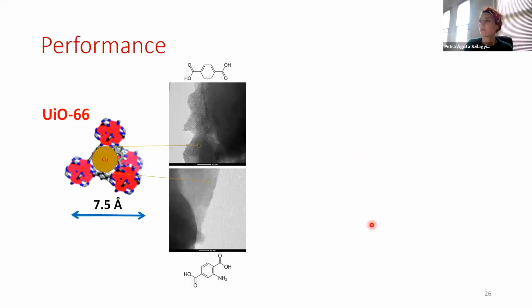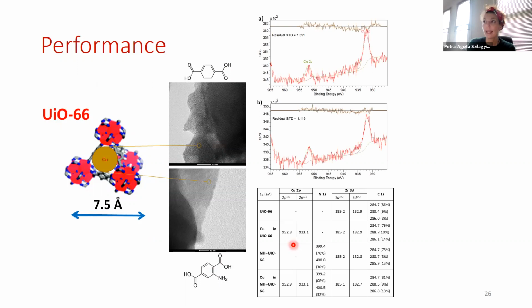So we devised this very simple system in which we took pristine UiO-66 and amino-functionalized UiO-66 as well, and we added copper nanoclusters inside the pores. In both cases, they were embedded in the pores. To test if there is any strong interaction which could give rise to electronic promotion, we also looked at the chemical state of copper, and we saw that there was no oxidation. In both cases, the binding energy was the same, and it also equaled that of metallic copper.